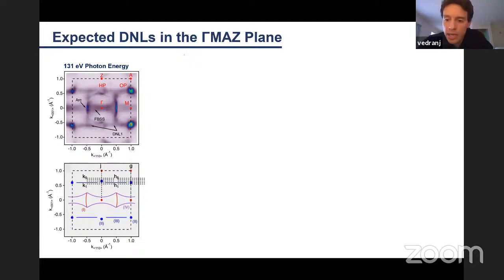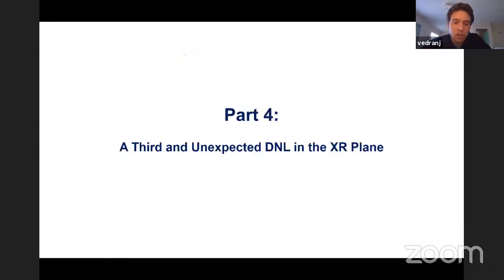But what I'd really like to show you is this third and unexpected direct nodal line. So as I mentioned, when we inspected the 110 surface plane containing the XR points, we found a third nominally gapped direct nodal line that essentially wasn't predicted by the density functional theory. And finding this direct nodal line was really tough.